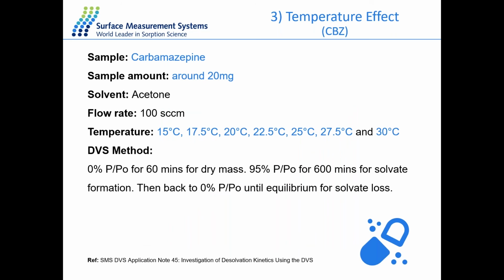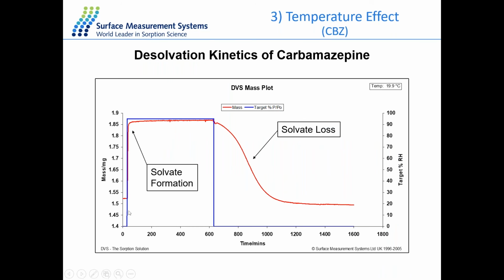And the last example is a very simple study with carbamazepine, where we use around 20 milligrams of the sample with acetone vapor at a range of temperatures from 15 to 30 degrees to study the temperature effect on the desolvation kinetics of the carbamazepine sample. We initially dry the carbamazepine sample at 0% partial pressure of acetone for about 60 minutes. And then we expose the sample to 95% acetone vapor for about 10 hours.